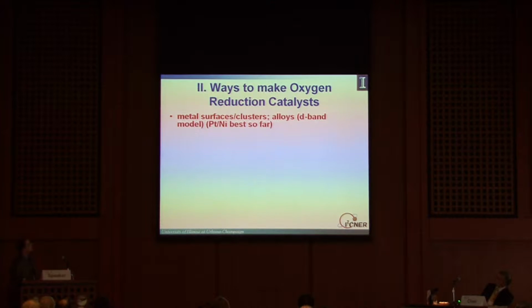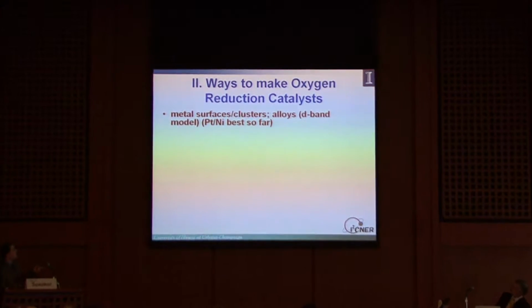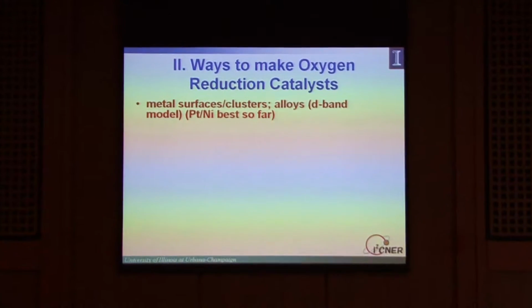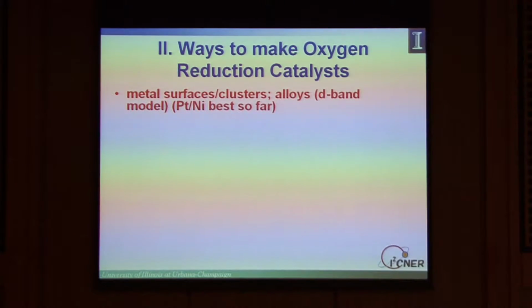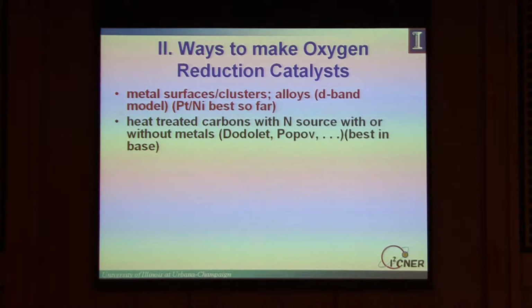Okay, so with this idea, how can we make new oxygen reduction reaction catalysts? Several ways. One way is by making metal surfaces or clusters or using alloys. The so-called d-band model, which is a consequence of something called the principle of Sabatier, important in catalysis, is often used. Platinum nickel is the best so far. We can heat treat carbons. All right, there is a lot of work this way. Dodelet is perhaps the most known for this. You can pyrolyze a carbon at 850 C and actually get something that works fairly well if you include a metal.